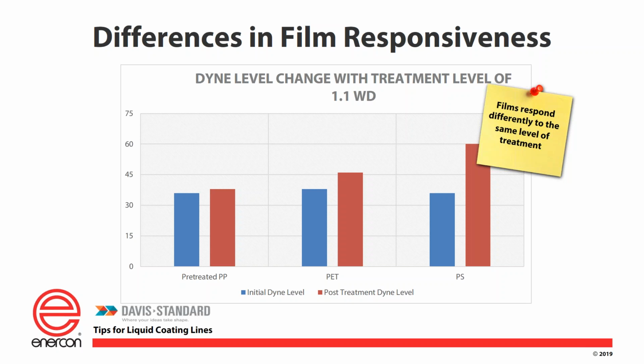Well, on the pre-treated polypropylene, we didn't get much, right? We got maybe 34 dynes or something like that. On the polyester, look at that. At a watt density of 1.1, that's a big winner by the dyne category. We got 45 dynes on the polyester. And the overall winner altogether in the dyne race here is polystyrene, where we went from the low 30s up to 60 dynes.